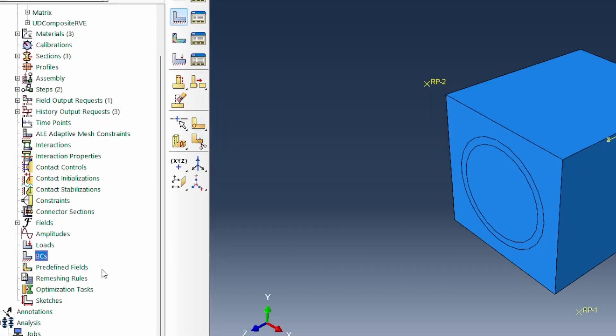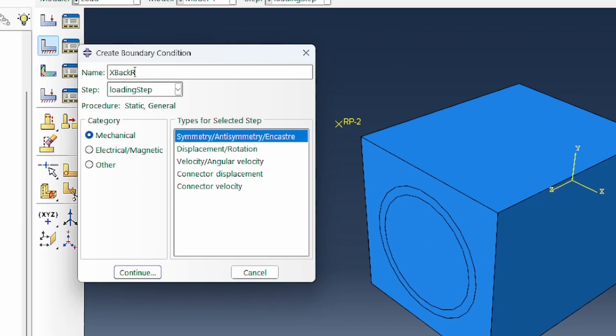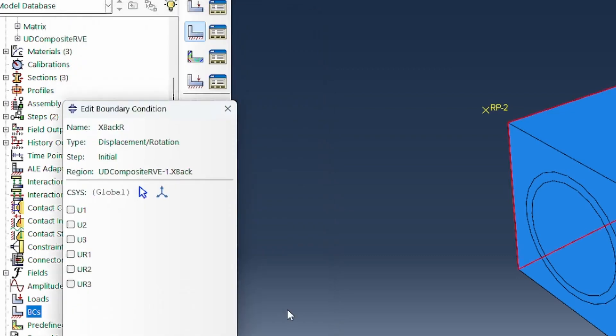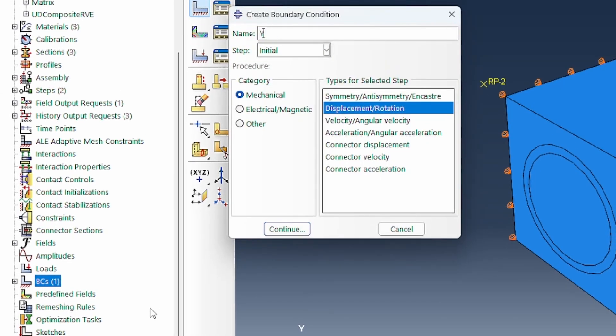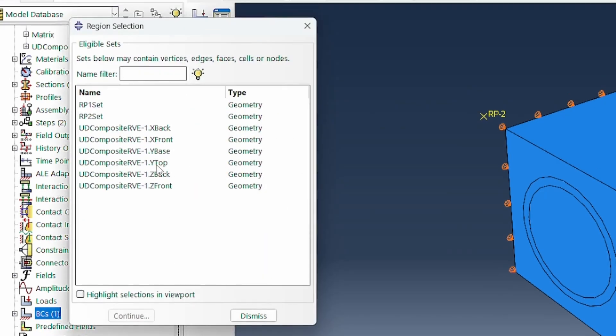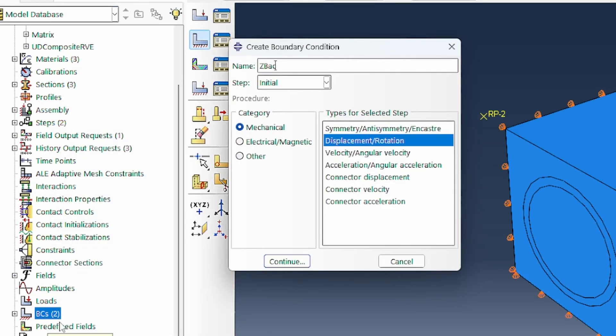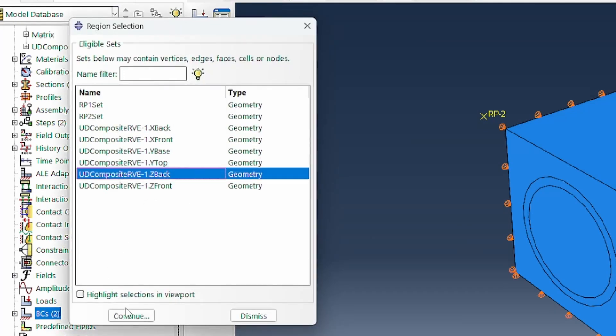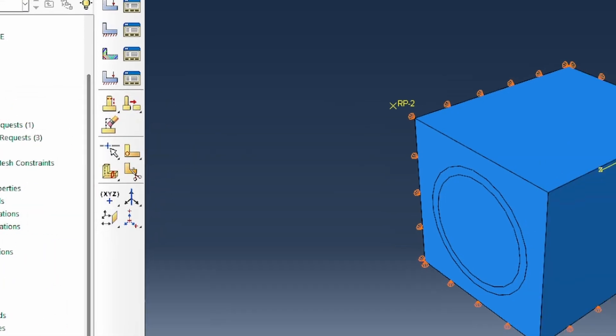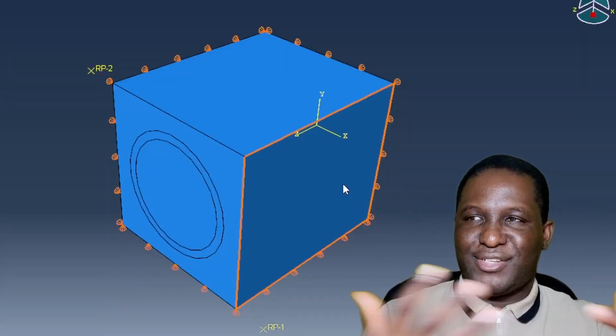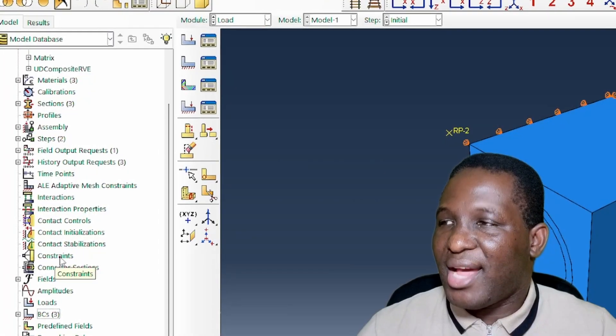Now going into Abaqus to set up the model. The first step is to attach boundary conditions. We call the x-back face a roller — fixing it only in the x-axis for the uniaxial cases. Then y-back roller, fixing it in the y-direction. Finally, z-back roller, fixing only in the z-direction. These are the roller boundary conditions that buffer the system on the non-loading planes.